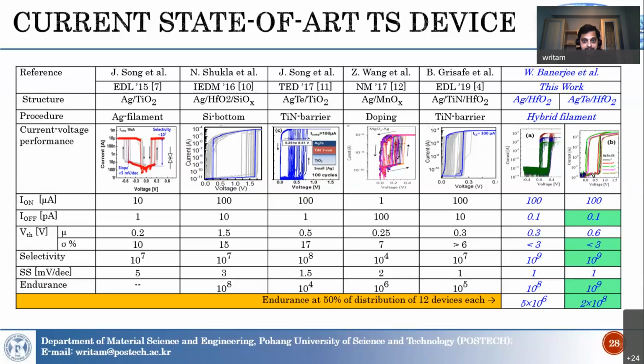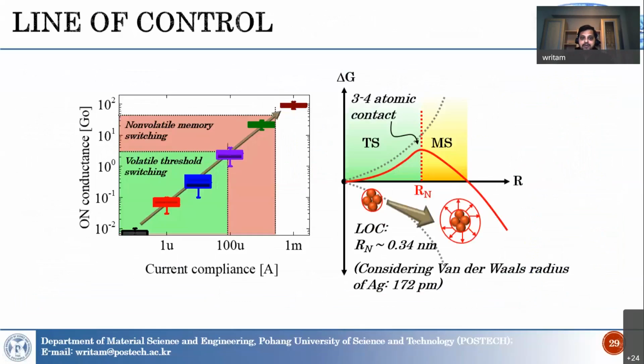Now the next part is that we can obtain this kind of behavior with a limited compliance, when the behavior is almost 100 microampere in that level. But when it exceeds that limit, more than 100 microampere, there is a widening of the filament, and that is the reason the switching is no longer volatile. The volatile switching goes to non-volatile switching, because you have a thicker filament.